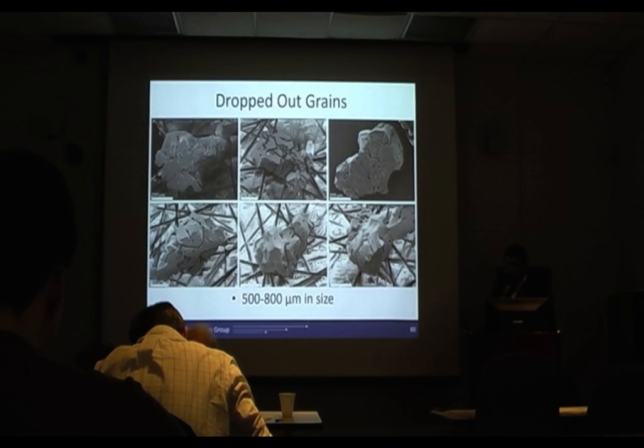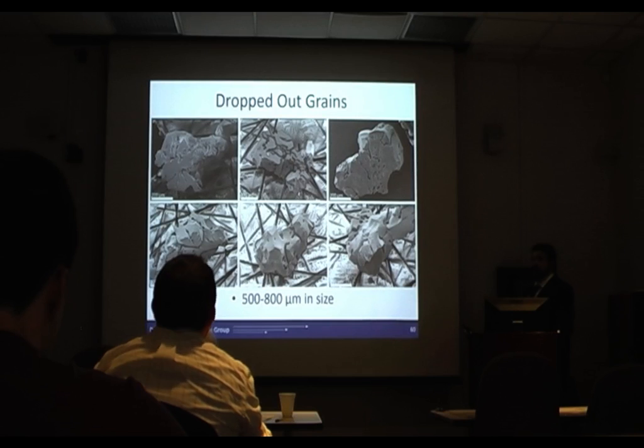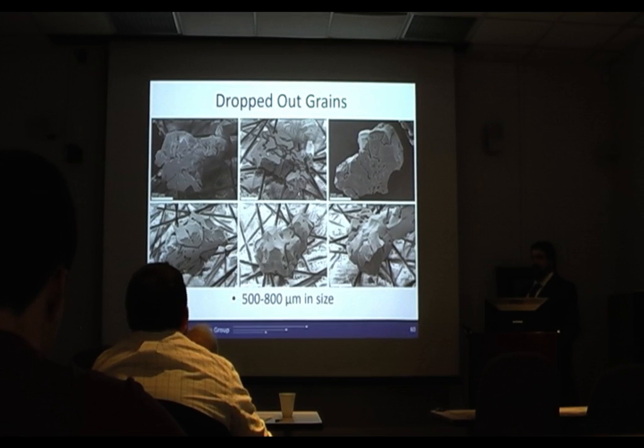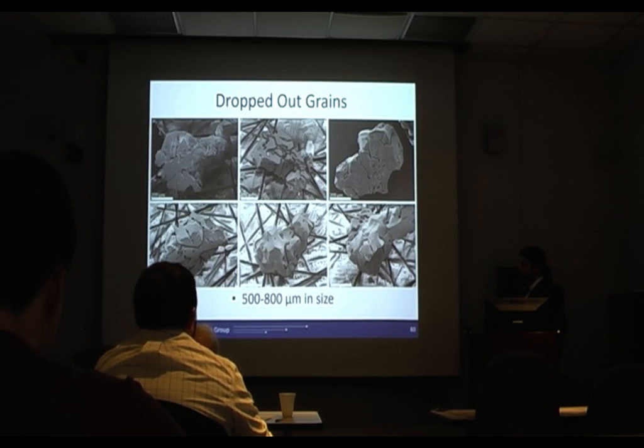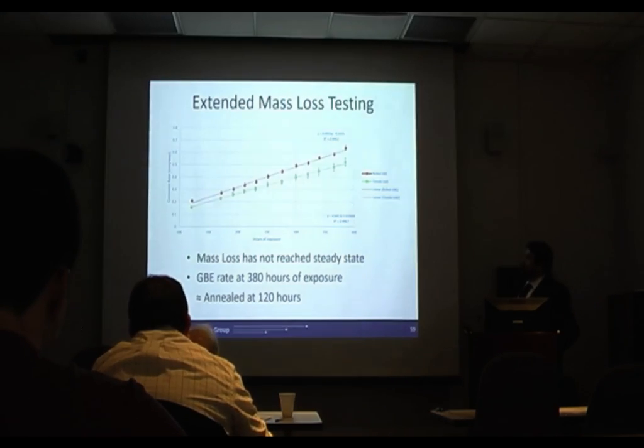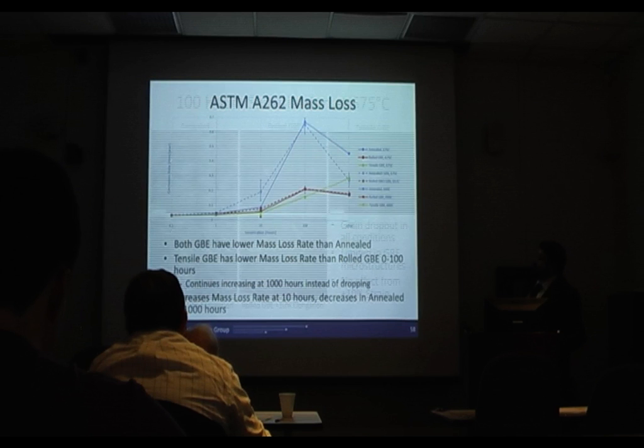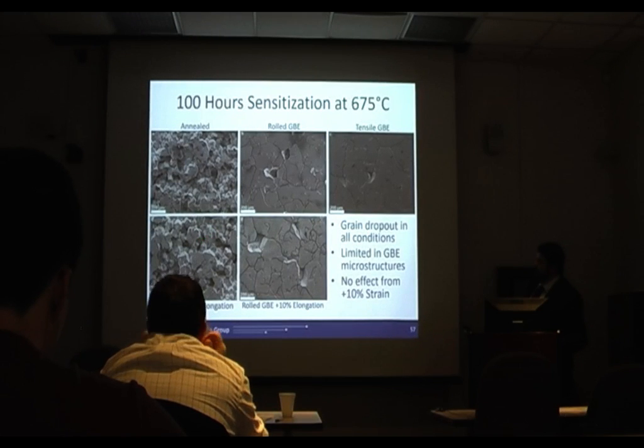And this is actually somewhat confirmed because I went fishing in our test rig for the grains that dropped out. And these are all from our grain boundary engineered samples. So actually, if I back this up to the 100 hour, you can see in the annealed, these are about 500 to 800 micron grains that dropped out.